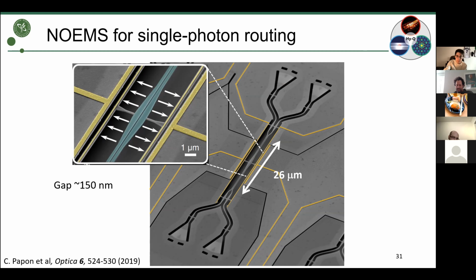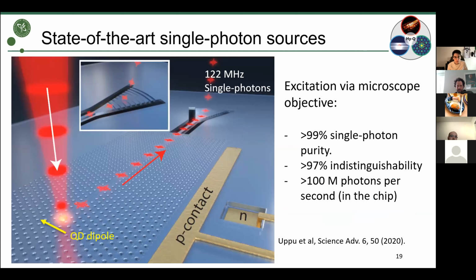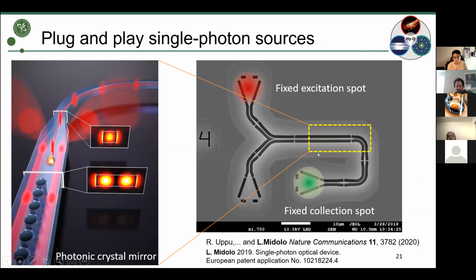Thank you. I didn't really talk much about this. It's a very good question. Right now it is indeed a challenge to have multiple quantum emitters that can all be integrated with each other. It's something we are starting to do only very recently. We have recent work that shows that we can probably do 2 for now. But 2 is already a good step, in particular if we can make it with this approach that I was showing here, because a device like this one potentially could be scaled. You could have several of these, and you can drive them all through waveguides. So you just use a single excitation spot and distribute this pump over different emitter sections. Of course, you will need to individually control the emission energy of each of these emitters, so that they all emit at the same wavelength, otherwise they're not indistinguishable.